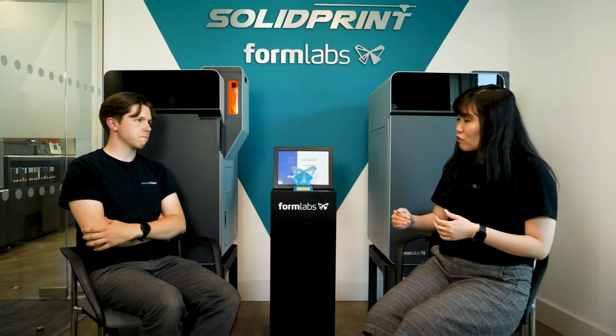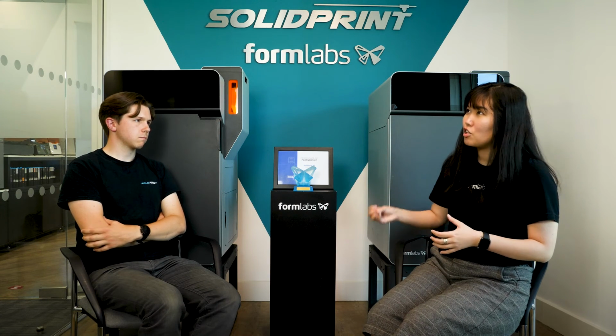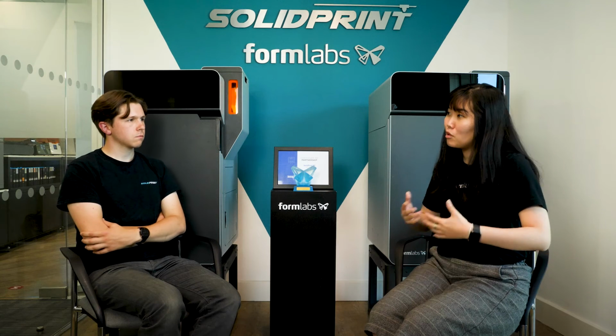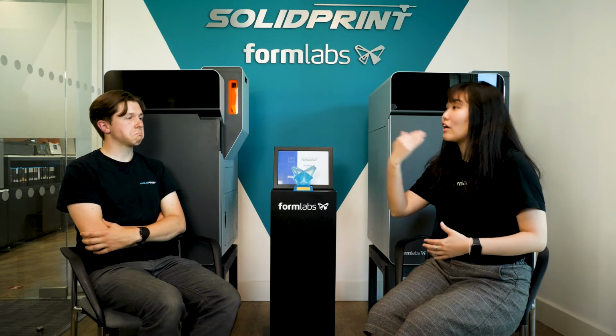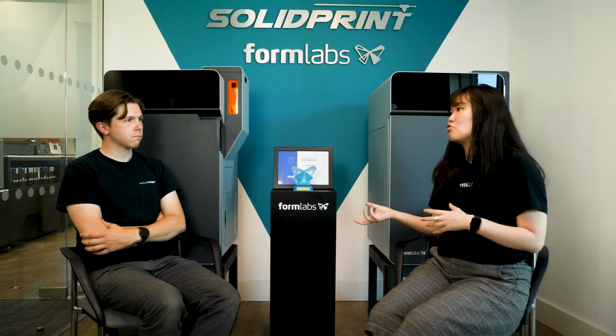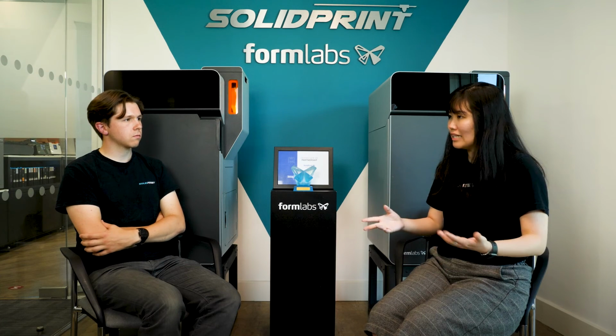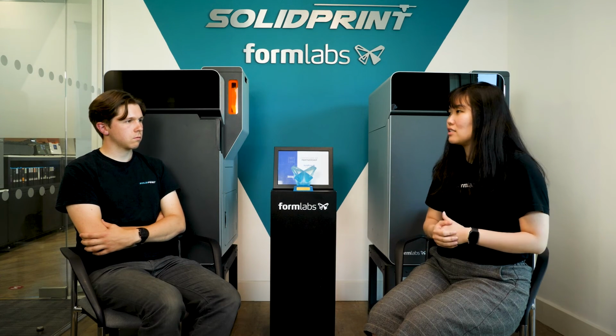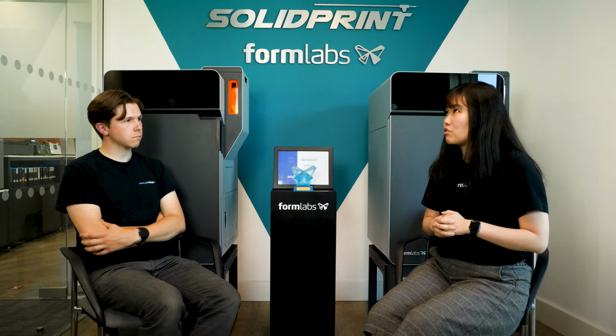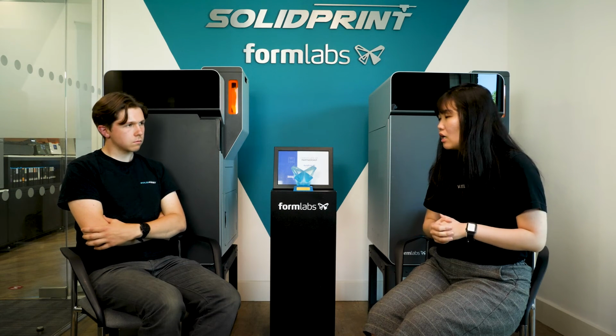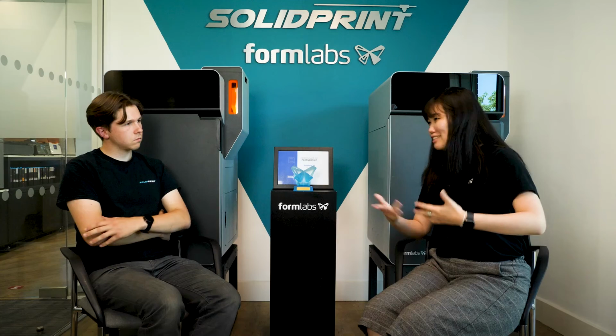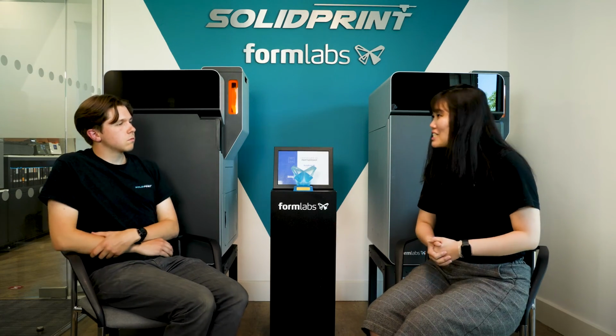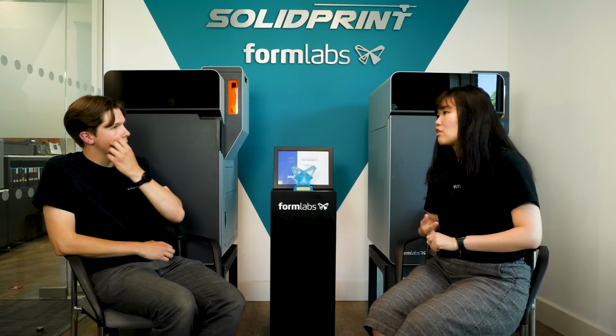Essentially, the lower the refresh rate, the less new powder you have to introduce to your reclaimed powder, so it's a little bit more eco-friendly. The higher the refresh rate, essentially you have to introduce more new powder. So to give you an example, Nylon 12 has a suggested refresh rate of 30% to 50%, meaning if I were to run a 10 kilogram print, which is the example I gave you just now, 7 kilograms reclaimed, 3 kilograms new.